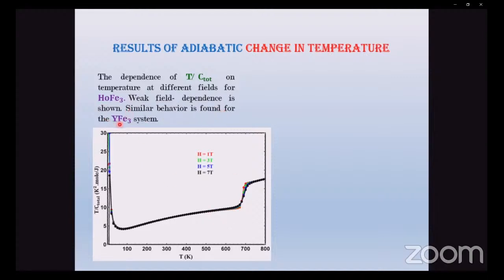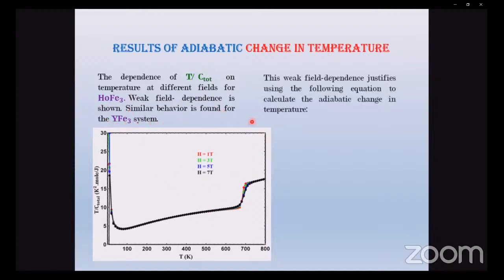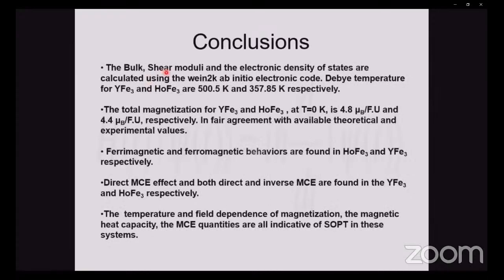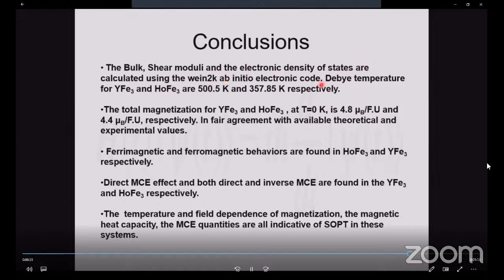Similar behavior is found for the YFe3 system. This weak field dependence justifies using the following equation to calculate the adiabatic change in temperature. Conclusion. The bulk and shear moduli and the electronic density of states are calculated using the WIEN2k ab initio electronic code.